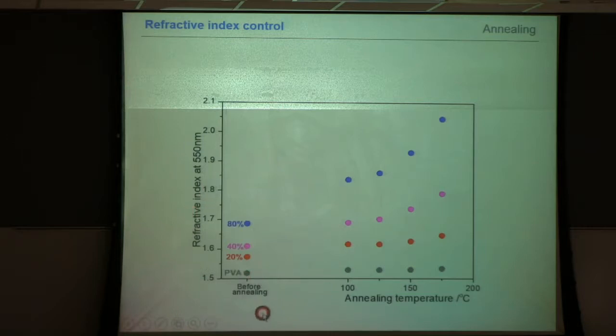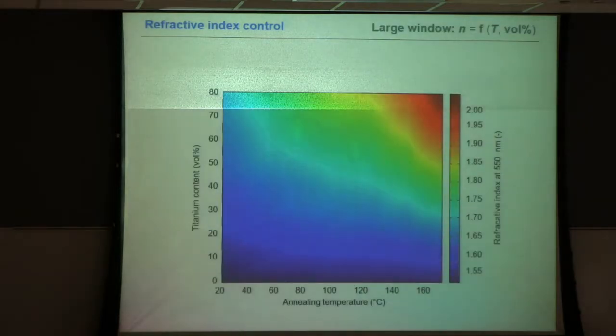And as a tool, what is nice, oops, that was too much. It's not only that we can manipulate the refractive index with composition, but also with heating. That's easily explained because we promote the condensation further, we densify the material, and especially for the high content material, we reach a decent refractive index of 2.1. And again, it's not the highest refractive index that really matters, but in case you have a material close to 2.1 and you use it with the lowest refractive index polymer that exists, which is 1.29, you get a very, very good refractive index contrast.